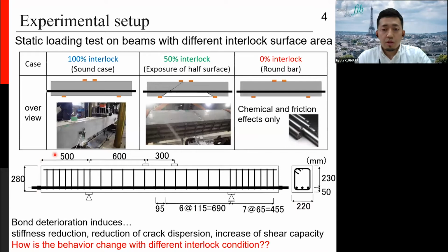So this slide shows the experimental setup. Static loading tests on beams with different interlocking conditions were conducted. The parameter was the interlocking area: 100%, 50%, and 0%. To achieve 50% interlocking area, this beam did not have the cover concrete from the casting. It means the bottom half surface of the main rebars was exposed like this picture, and in this area there was no contact with concrete. In the 0% interlocking beam, a round bar was used as main rebar, so it had only the bond effect by chemical adhesion and friction action. All beams were designed to fail in shear to catch bond performance.